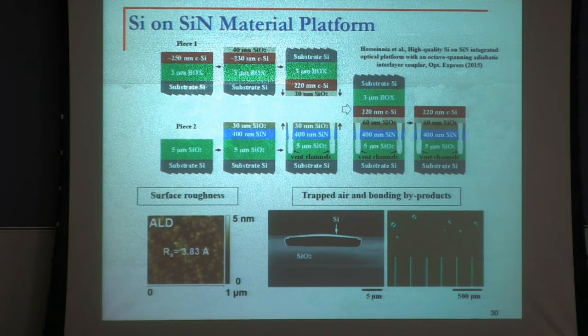So here is a silicon on insulator wafer again. Here is an oxide on silicon. And then we grow silicon nitride here at IEN using the LPCVD technique to have a high quality silicon nitride. And then we put oxide on the top, we bond the two, and then we remove the substrate and the oxide, and we get silicon on nitride.